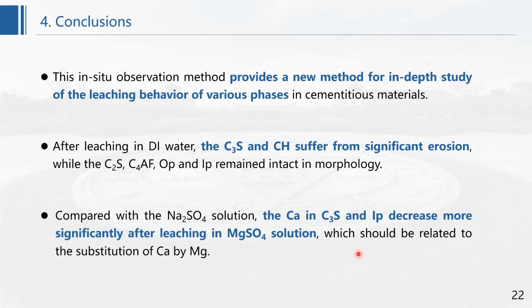Now we come to the conclusion part. Firstly, this in situ observation method provides a new method for in-depth study of the leaching behavior of various phases in cementitious materials. Secondly, after leaching in deionized water, the C3S and CH suffer from significant erosion, while the C2S, C4AF, outer product and inner product remained intact in morphology.